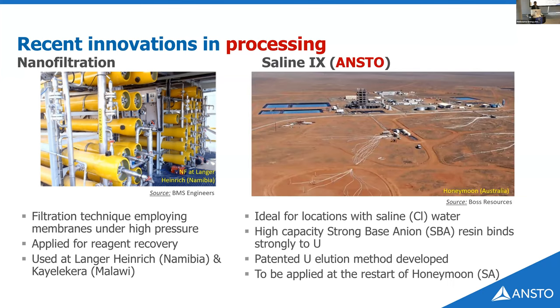The other thing I've got here is saline ion exchange, in brackets ANSTO, because my colleagues James Quinn and Karen Seldenhoff have been involved in this work at ANSTO. And it's ideal for locations that have got saline or chloride containing waters, right? There are high capacity strong base anion resins that strongly bind to the uranium. Because they bind very strongly, they have a tendency not to release the uranium when you're trying to remove it for a precipitation process. But ANSTO has developed a technique where you can transform it, and it allows you to take it off the resin. And that technology will be deployed at Honeymoon in South Australia.